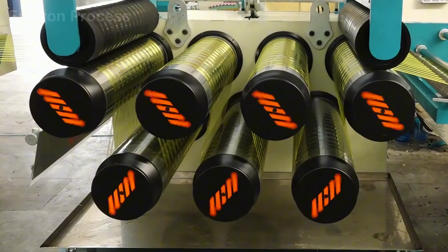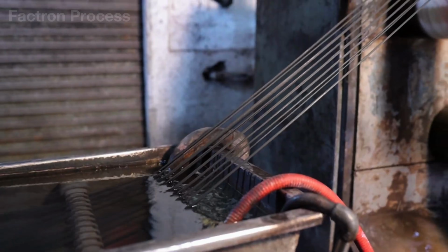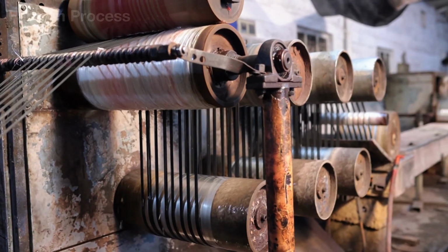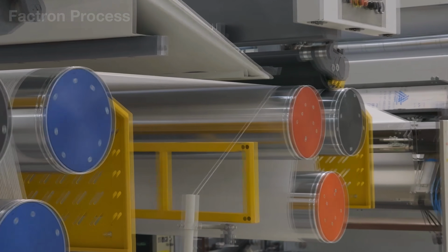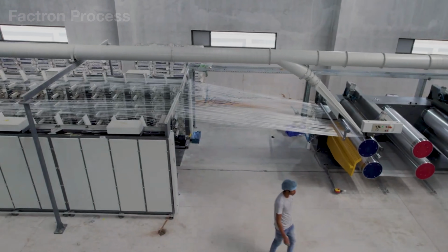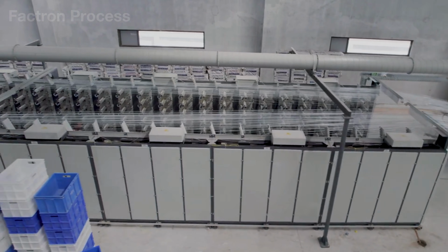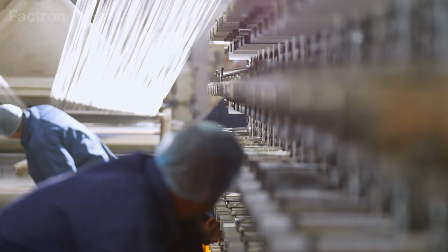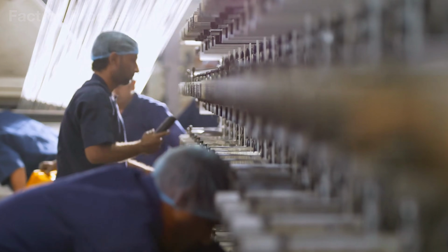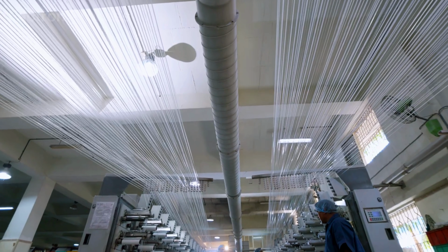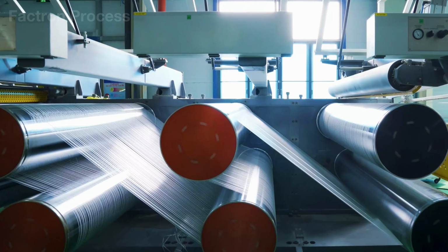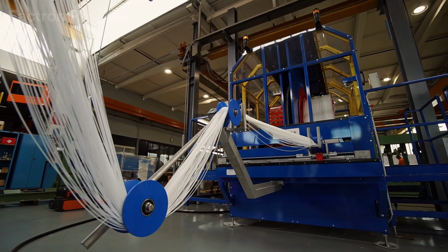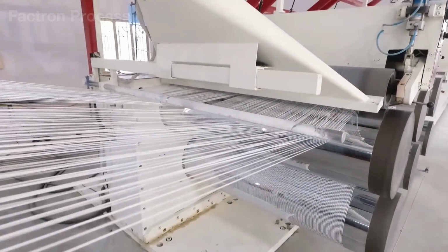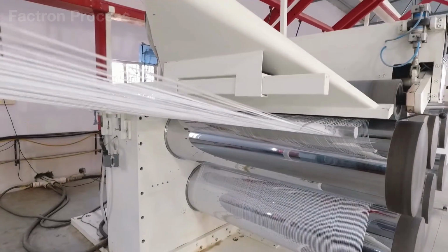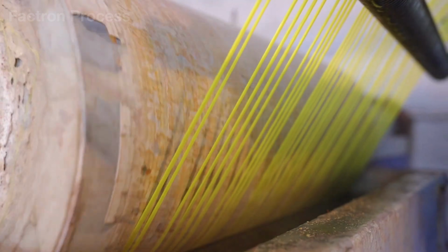The key principle lies in the difference in roller speeds. The downstream rollers rotate faster than the upstream ones, stretching the filaments at speeds ranging from 400 to 1300 feet per minute. This continuous speed differential elongates the filaments to approximately 4 to 7 times their original length, forcing the polymer molecular chains to align almost perfectly along the fiber axis. As a result, the fibers become stronger, less stretchable, and far more resistant to tensile loads.